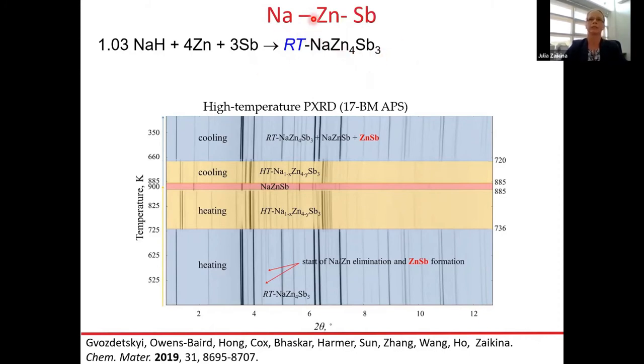But then we were curious, what is the best synthesis temperature to make this compound, and so we brought the sample of it to the Argonne National Lab, and here we've collected powder X-ray diffraction data by increasing the temperature, and surprisingly, at a temperature of 736 Kelvin, we saw the drastic transformation of the powder pattern into something else. And then further heating gave us this 111 compound, this thermodynamically stable compound.